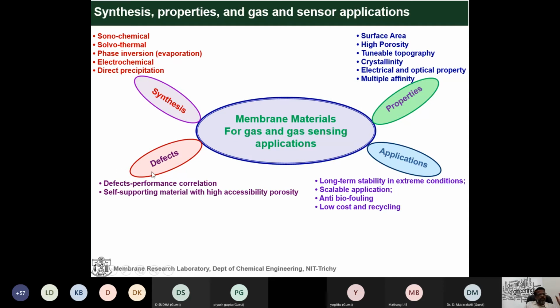Then you look at the defects. What are the defects when you apply them to a membrane? For example, the agglomeration effect, the aggregation effect, not uniformly distributed on the surface of the membrane. In addition, sometimes you can't make the membrane; there is a lot of rolling effect and different defects. Then you avoid all those things, and you can make this membrane for high accessibility, porosity, and application. The applications: long-term stability, extreme conditions, scalable applications.